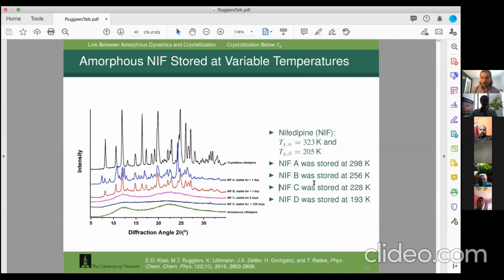I really want you to focus on sample C and D. Sample C was stored at 228 Kelvin, which is 23 Kelvin above the beta transition temperature. Sample D was stored at 193 Kelvin, which is 12 Kelvin below the beta glass transition temperature.